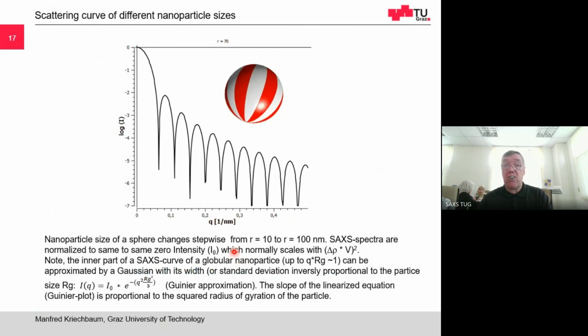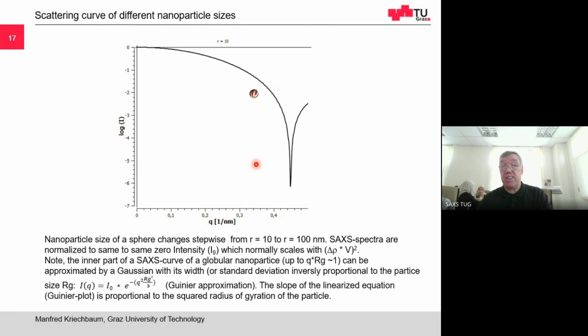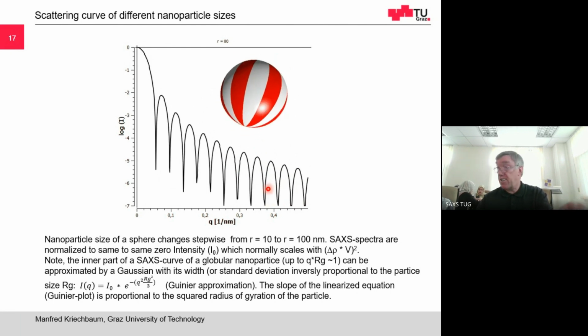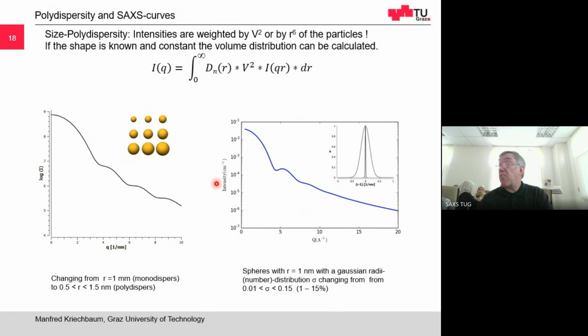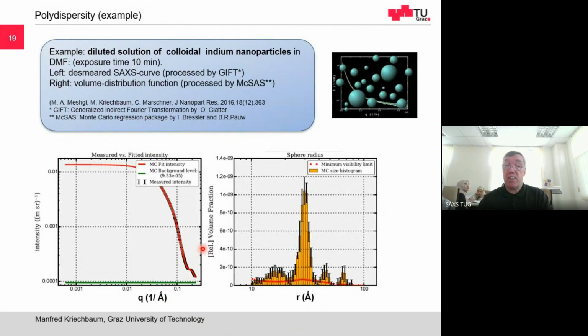Okay, here's just an animation of how this scattering curve changes in space. Large particles scatter to small angles and small particles to large angles. That way, the scattering curve will change. Here, if we have polydispersed particles, the scattering curve gets more diffuse. Monodispersed, sharp maxima and minima; polydispersed, diffuse scattering. This is an example. So you can also study polydispersity. If you have the same shape, so this was in a publication we did maybe 5 years ago. These were nanoparticles of some indium particles synthesized. And we nicely get a size distribution of these nanoparticles by small angle scattering from this SAXS curve.